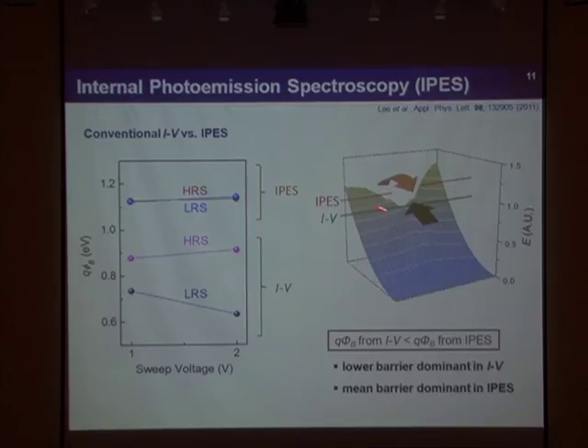But actually, if there are no big changes in the average value, since the current is proportional to the area, we can estimate the mean barrier height. So this difference means inhomogeneity of the barrier height.